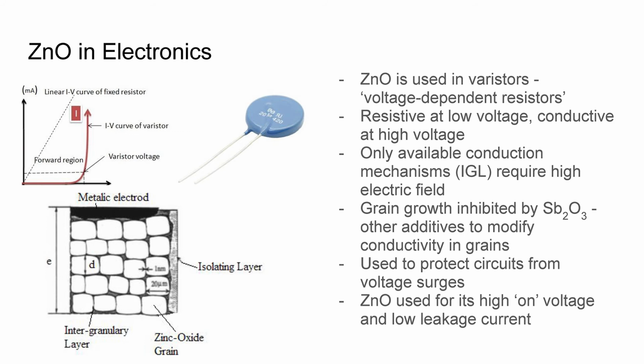So those little grains are sintered zinc oxide particles, and the layer between them is a mixture between zinc oxide and Sb2O3, which is also an additive to inhibit grain growth, so they can actually tune the size of the grains and the breakdown voltage, and it stays like that. The grains don't grow and change over time. But the main use for these is to protect fine circuitry, because you don't want to design a circuit for a voltage spike of 300 volts, so you want to protect it with one of these. So you would put this in between the supply and ground, so that if there's a huge voltage spike in the supply, it all conducts through this instead of going through the fine circuitry.